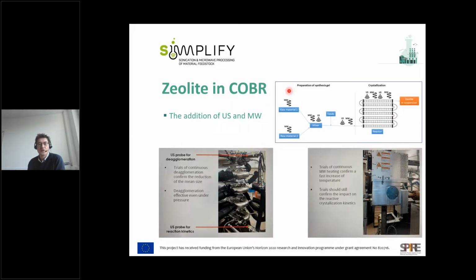We can have, for example, microwaves present for heating of the different feed materials, but also along the COBR. We can also have ultrasound in the mixing phase, and again also within the COBR for nucleation enhancement of the zeolite nuclei, or also for deagglomeration of the formed products. A picture shows a little bit how this is integrated. So here you see the bends of the COBR. We're able to put the sonotrode at the bends. This is at the beginning of the COBR, where we're using the ultrasound probe for reaction kinetics enhancement. More towards the end of the reactor, we're using ultrasound for deagglomeration.